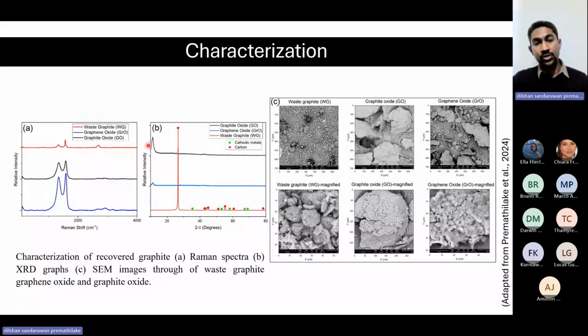In the XRD patterns, you can also see that the graphite peak, which is supposed to be at 25 degrees, has shifted towards 10 to 11 degrees. This is the identical signature of graphite oxide and graphene oxide. In the SEM images, you can see that the graphite oxide contains lots of whitish, very light color. This is because of the high amount of active sites attached to the graphite structure, which is very helpful in absorbing many pollutants from wastewater. The graphene oxide, on the other hand, contains a few active sites, because most of them are detached from the graphite structure when the sonication takes place. But you can also see that the particles are fragmented, which means the surface area of this material is really high, which can trap lots of pollutants.